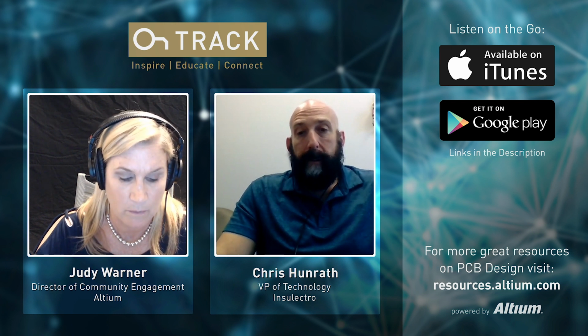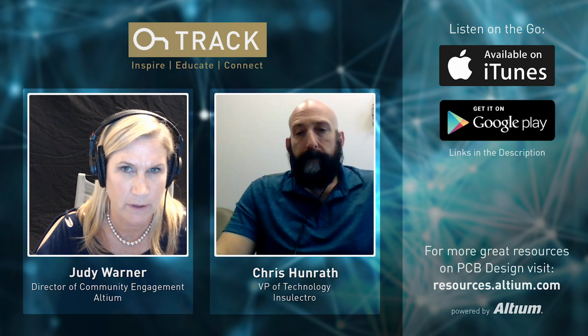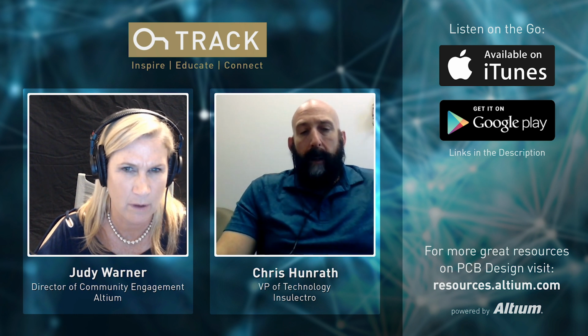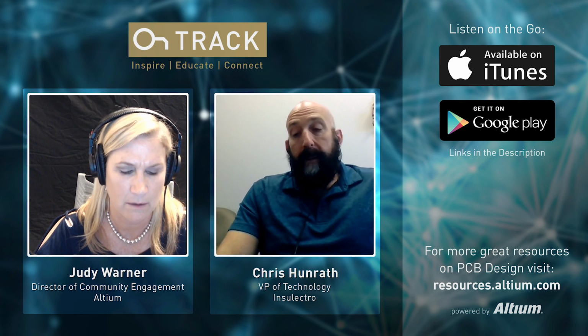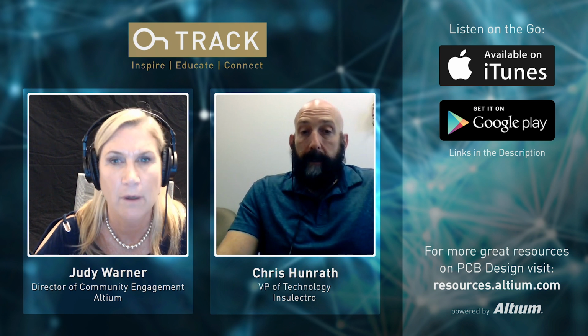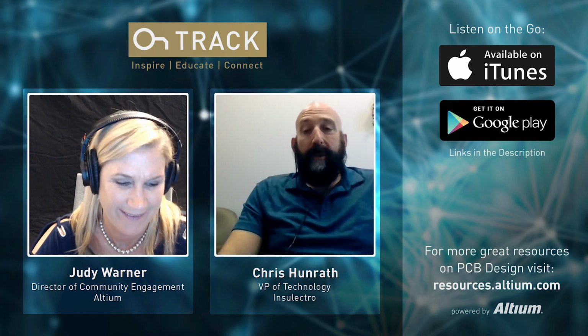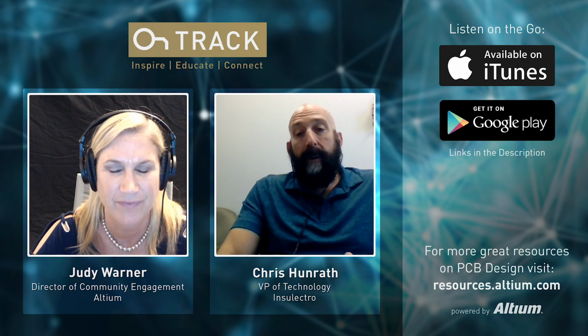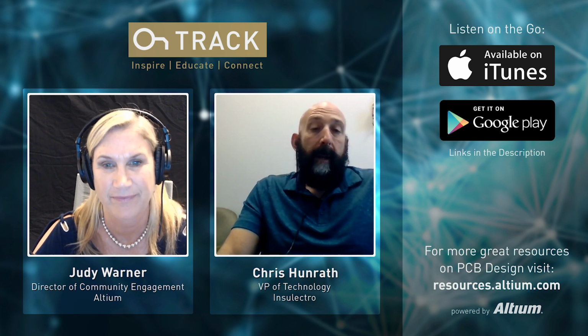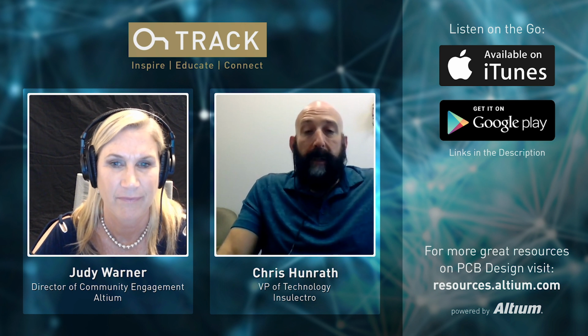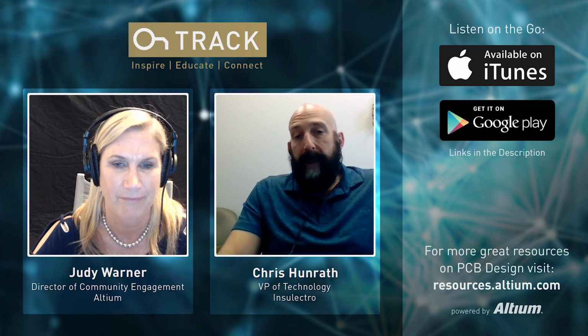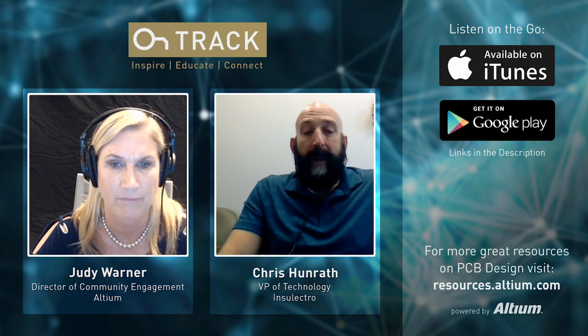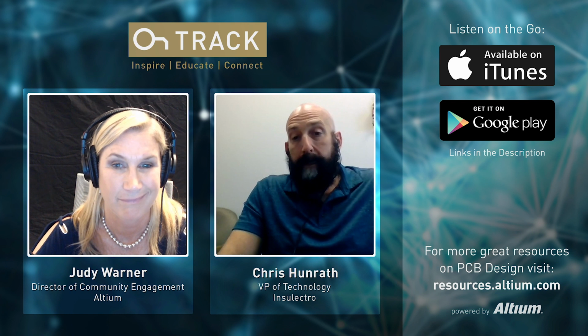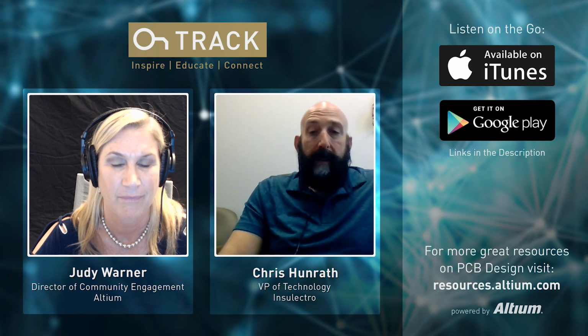Interesting. So, I think you mentioned too there's some good signal integrity benefits. Did we cover that? I don't recall. No. So one of the things that a lot of designs call for is something called back drill. You're familiar with that. So you do the back drilling to get rid of the unwanted copper. So again, in my earlier example, let's say you're connecting layer 1 and 10, and let's just say it's a 26 layer multi-layer. You're going to have a lot of extra copper metal in that via that you really don't need or want. So common technology is to back drill down to layer 10. Now, of course, drilling to that precise location or depth, to remove the copper up to layer 10, but not beyond it, because of reliability concern, that's a bit of a challenge.